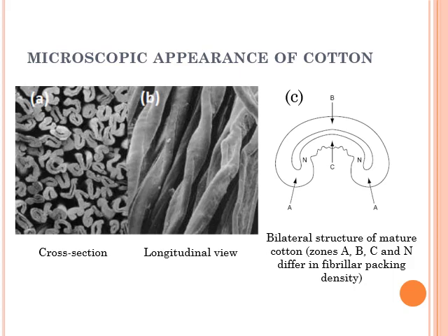The mature cotton fiber forms a flat ribbon varying in width between 12 and 20 micrometers. It is highly convoluted, probably on account of the twisting that takes place when the tubular shape formed during growth collapses on drying. The number of convolutions varies between 4 and 6 per millimeter, reversing in direction every millimeter or so along the fiber.